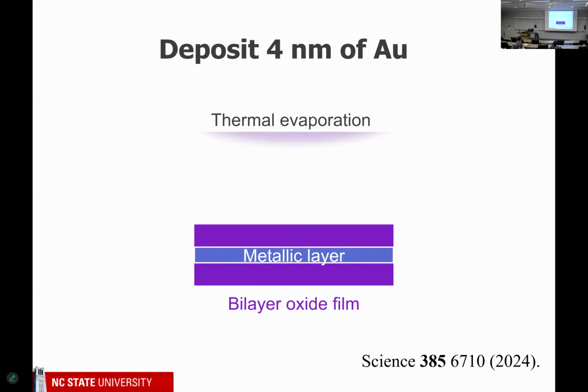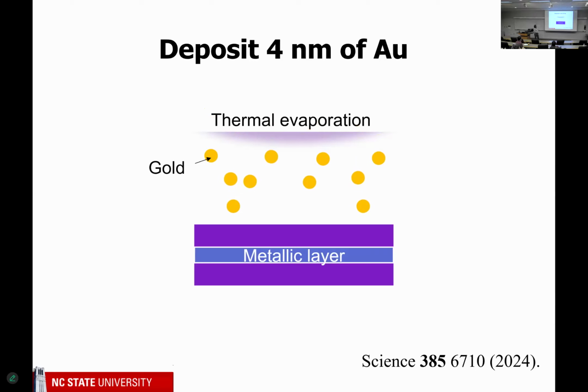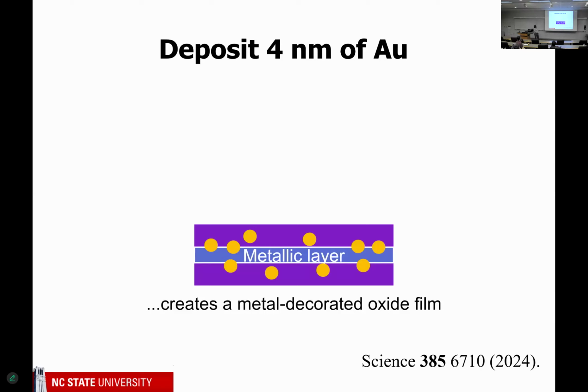So we took this bilayer film, and we put it in one of those chambers I described to you, and we deposited 4 nanometers. It's like nothing. It's like a little dusting of gold. So here come our gold atoms. We deposit on there. And it turns out that metal sort of gets incorporated into the film. We call it metal decorated. It's kind of a silly word, but I need to give you a little bit of background about why this ends up being so interesting.